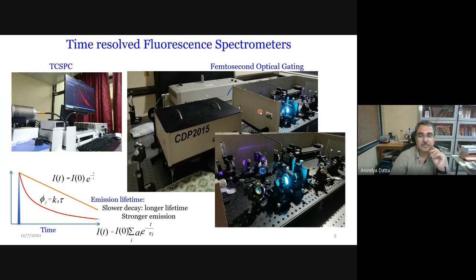Now, to do this, we use mainly time-resolved spectroscopic techniques. Once again, to this audience, I suspect we do not really need to introduce these. If you want to look at fluorescence or photoluminescence dynamics in nanosecond to hundreds of picosecond time scale, then we use this highly celebrated method called time correlated single photon counting, TCSPC. And if you want to go down to hundreds of femtoseconds to a few picosecond, maybe 100 picosecond or so, then we use what is called femtosecond optical gating.